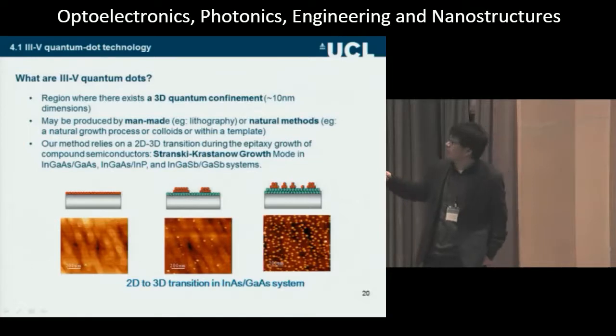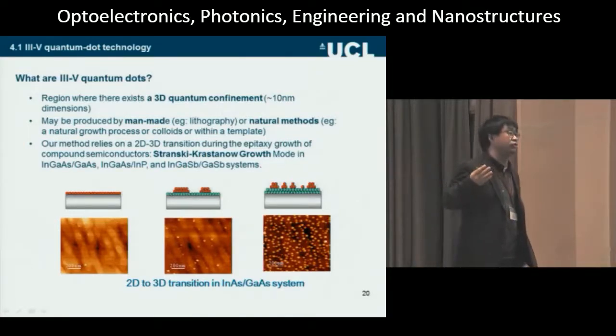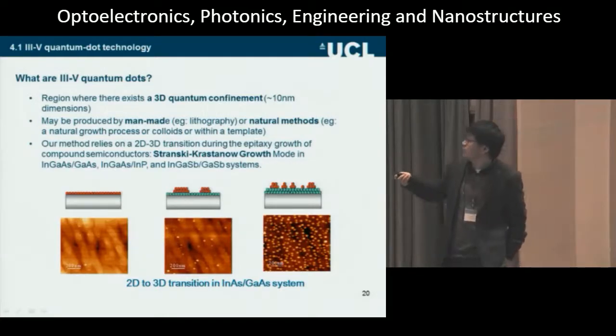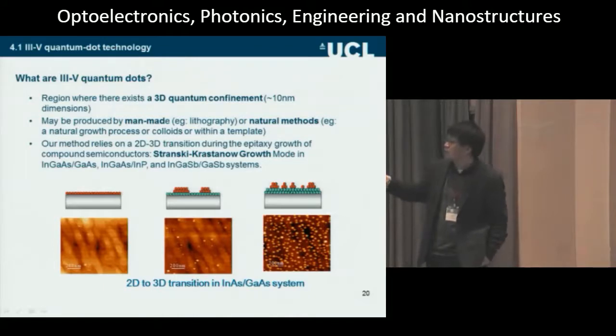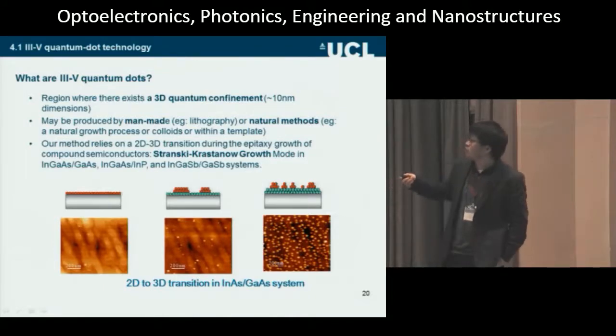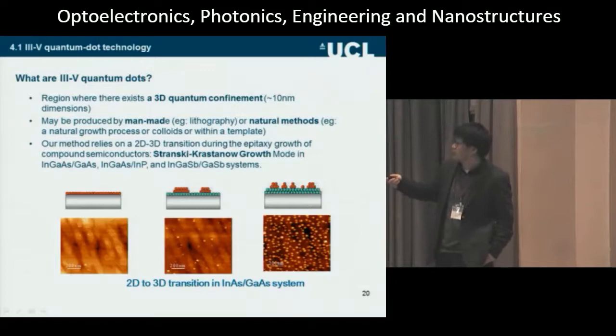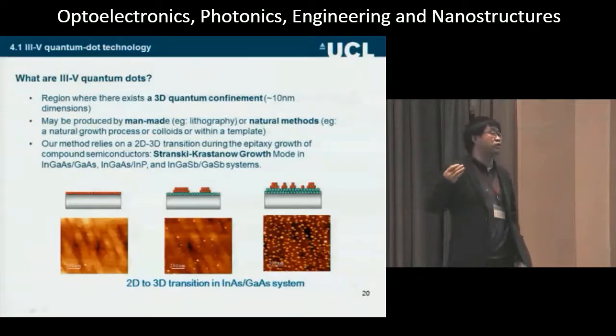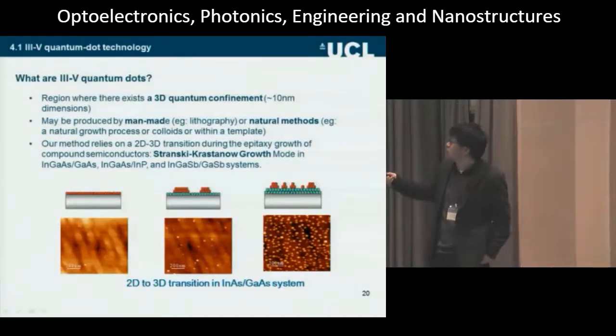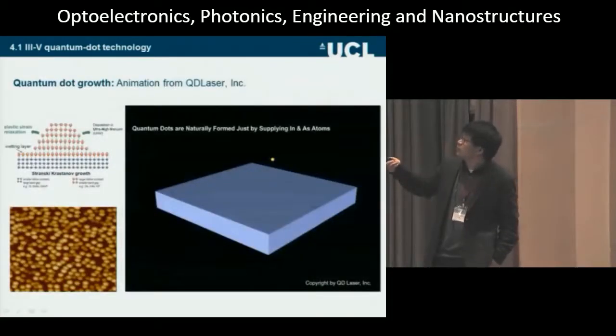Actually, this approach, I have to say, was mainly developed by one of the pioneers from the Ioffe Institute here. Basically, what you do is grow indium arsenide on gallium arsenide. For the first layer, you get a flat surface. With further growth, you get a 2D to 3D transition and get low defect, low density quantum dots. These are mainly used for quantum single photon source technology. With further growth, you get very high density and uniform quantum dots.